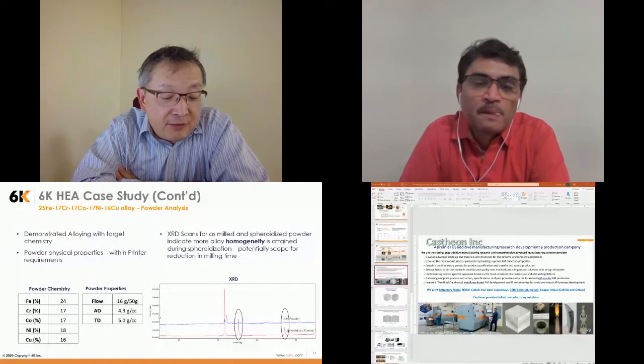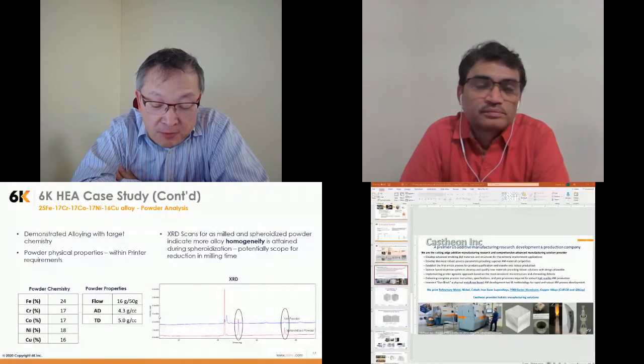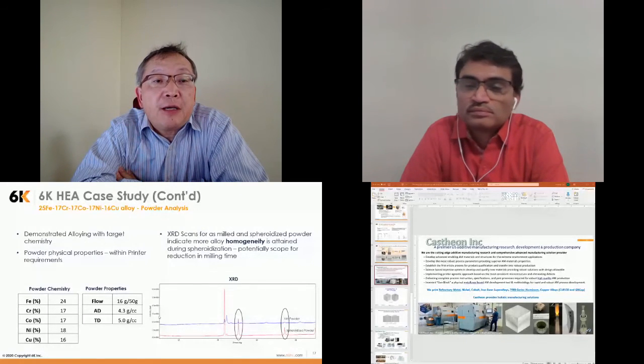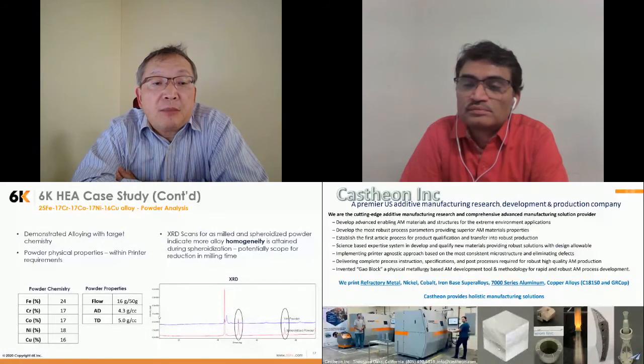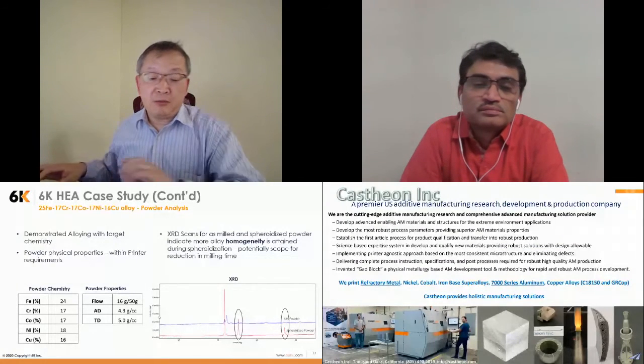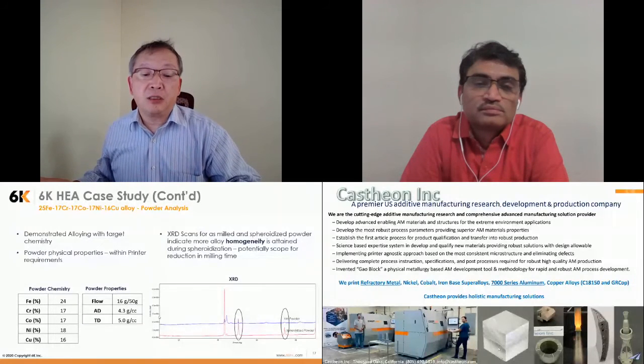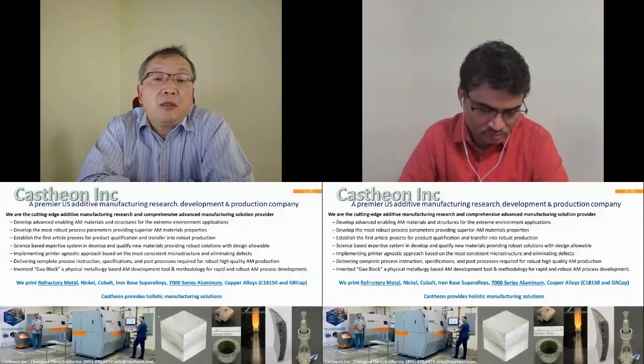Castheon is funded for the sole purpose of advanced additive manufacturing and to do in-depth additive manufacturing study, from the grain morphology control to the process robustness for defects and defect elimination. And so we do a lot of high temperature material. My background is in the rocketry industry, so we do a lot of high temperature material, refractories, nickel, cobalt, iron-based superalloys. We also do 7 series aluminum and coppers as well, GRCop for the rocketry combustions.